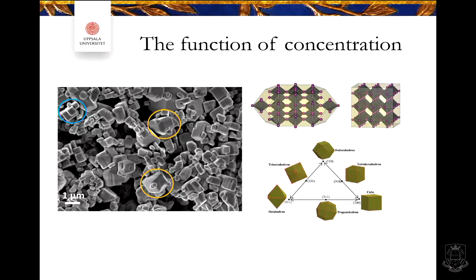Another thing that I found in those solutions was that the molar residue concentration between the components was important for the growth. So for instance, if there was a lack of MAI, you also got these truncated cuboid systems. You have different planes in which it's growing. While if you have a large quantity of MAI around, it prefers to grow into those cubes.